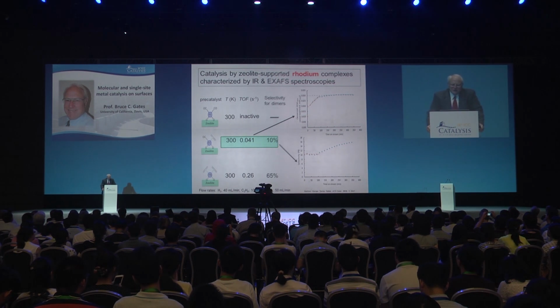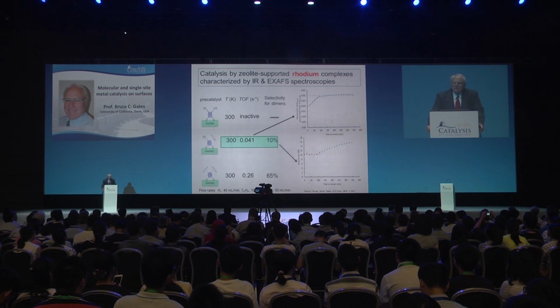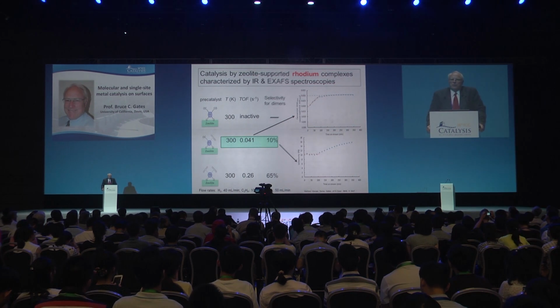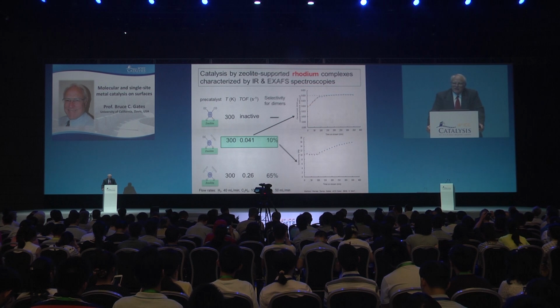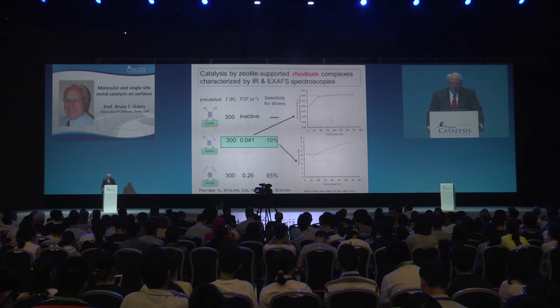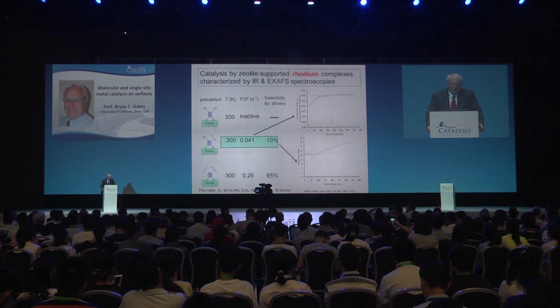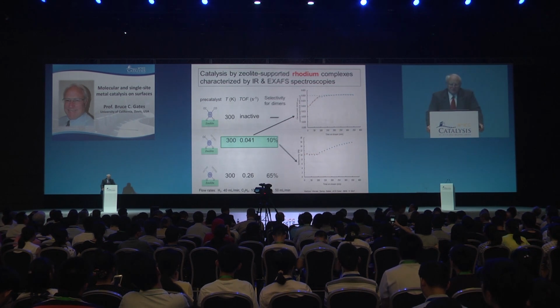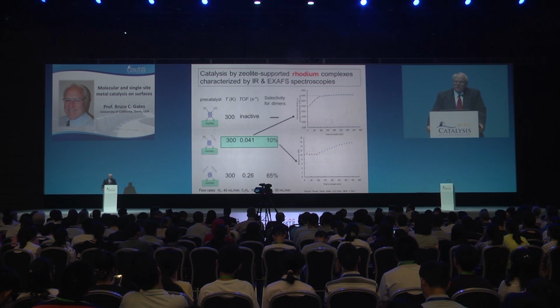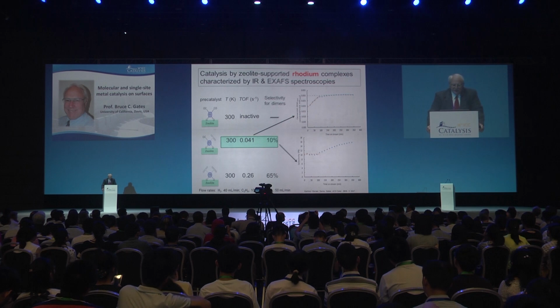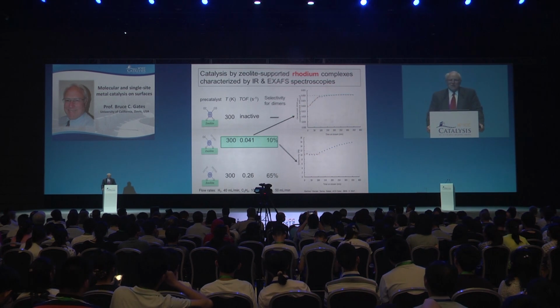The turnover frequencies: the gem dicarbonyl is catalytically dead. Of course, CO is a poison. The diethylene complex gives a relatively highly active catalyst, and the one in between gives catalytic performance in between — no surprise. The activity and the selectivity both change depending on the ligand environment of the pre-catalyst.